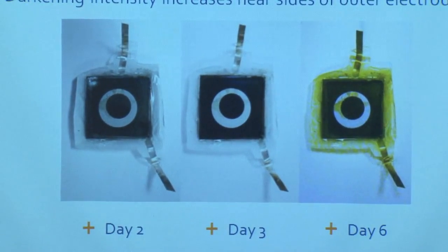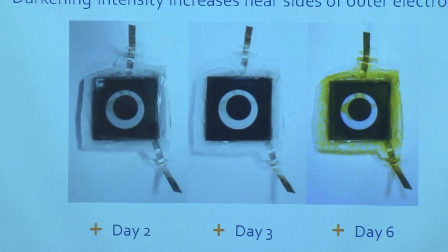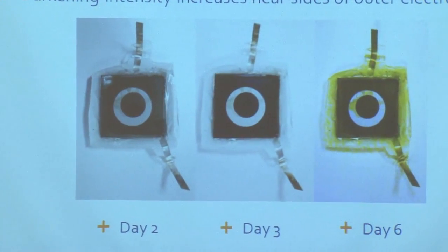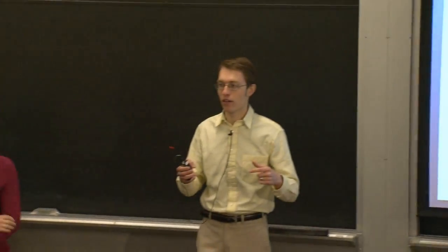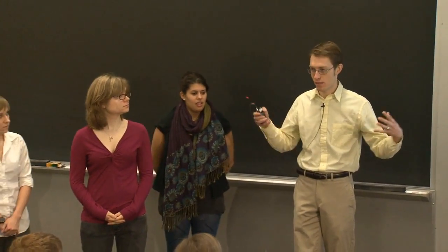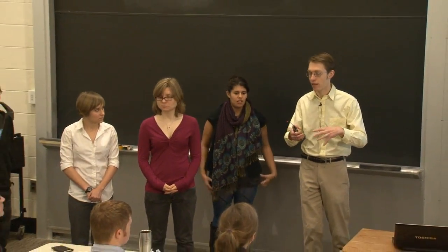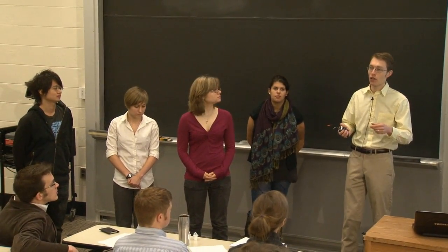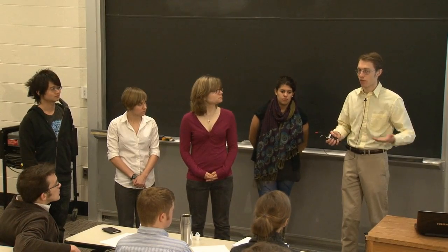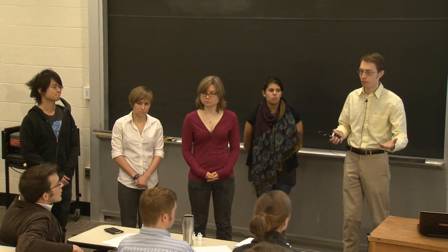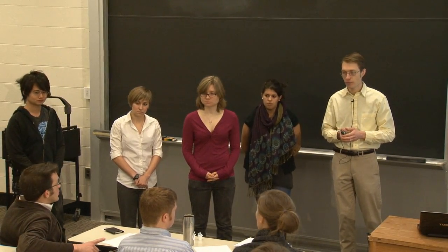So that to us says that there's definitely something happening here where the atmosphere is leaking in through the encapsulant and reacting with the device, because that will happen from the outside in, as opposed to a reaction with the encapsulant itself or a thermal process which would affect the whole device uniformly. And this was EVA? Yes.